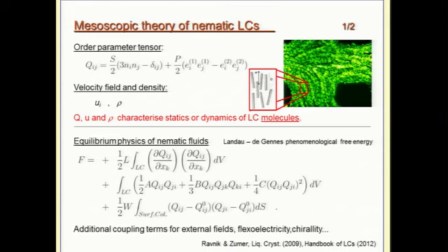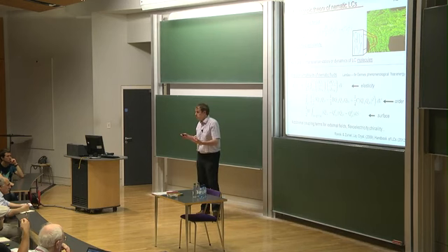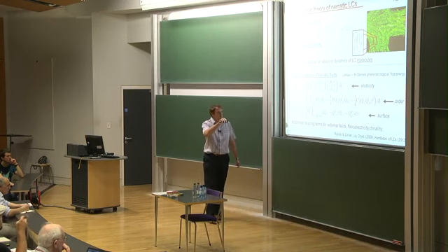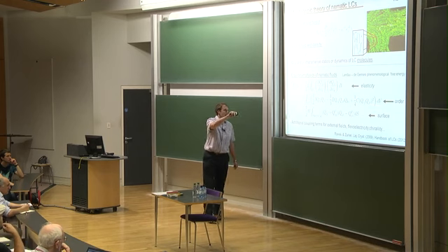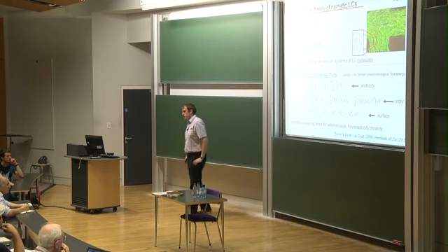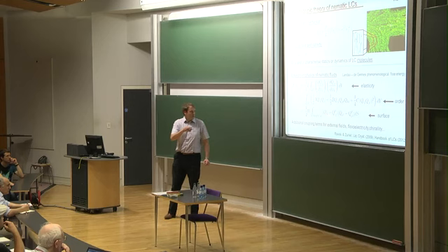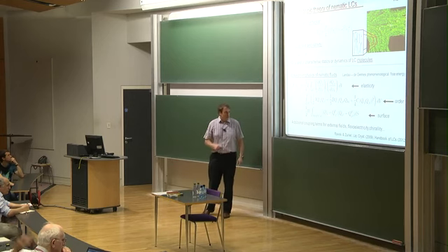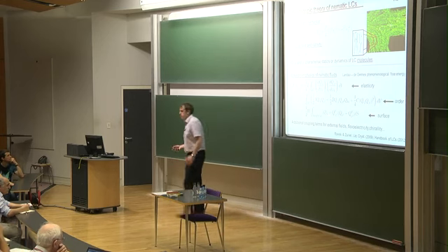Now, in order to approach the various structures, colloids in liquid crystal, at this micrometer scale, a very strong approach is to use free energy modeling. And we have used this for a long time. There are 3 basic ingredients which you need to put in: the elasticity, the order, the Landau term, and also the particles need to couple with the liquid crystal.